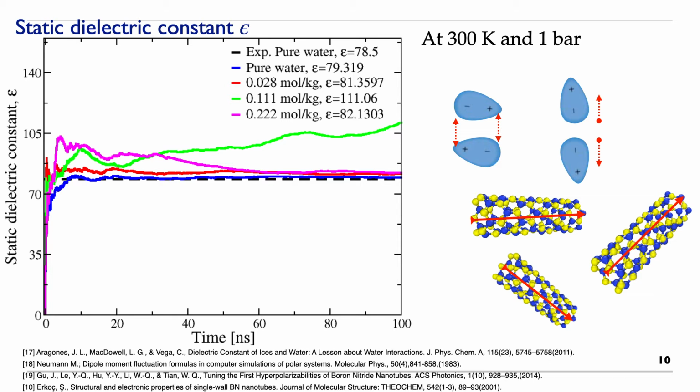Now we calculate the value of the dielectric constant for the mixture and compare how much it changed with respect to pure water. In general, we observe an increase in the value of the dielectric constant, since the charge distribution in zigzag type nanotubes is a dipole. Since in the nanotube each atom has a charge and forms a dipole, the interaction between water molecules and nanotubes is in the form of dipole-dipole.